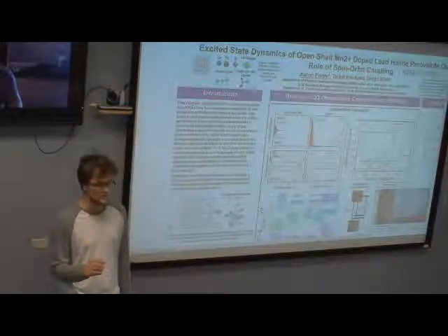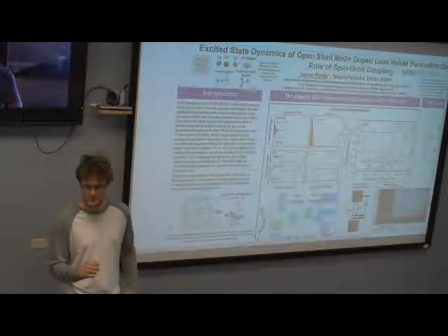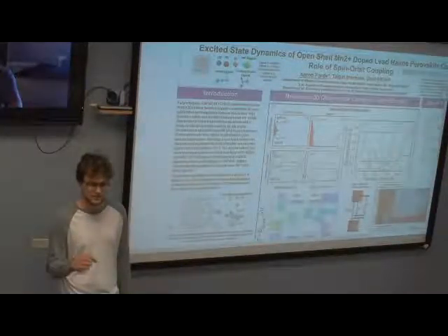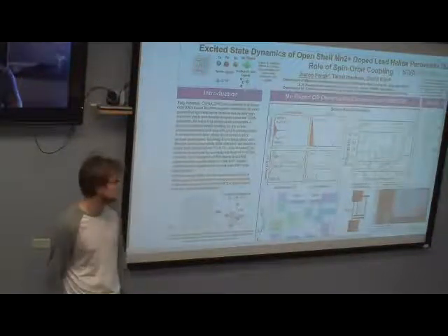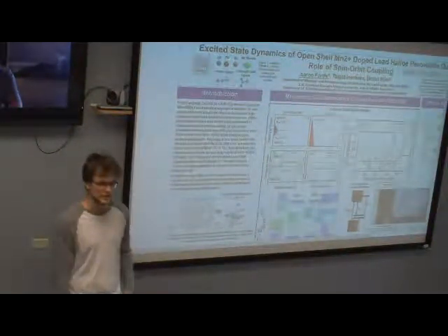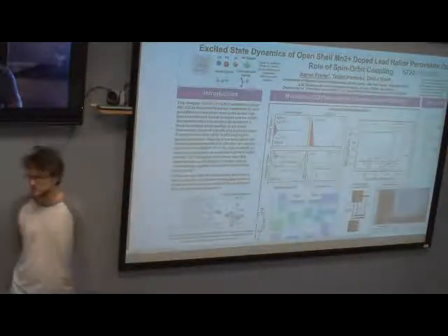We have to use more sophisticated methodology than what's typically used. So we use spinor Kohn-Sham orbitals, because spin orbit coupling facilitates the spin flip transition for transition metals. If you don't have spin orbit coupling, you can't model spin flip transitions. So we include that in our methodology. And I didn't highlight it earlier, but this is our model up at the top. It's our perovskite quantum dot, and in the very center it is doped with a transition metal, and it has a bromine halide field around it.